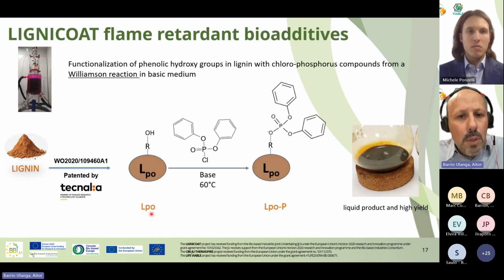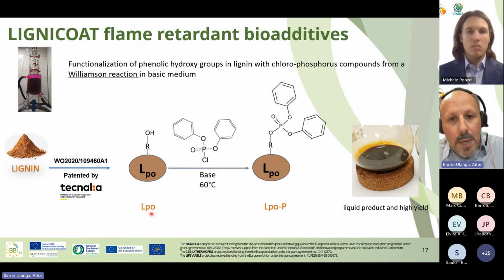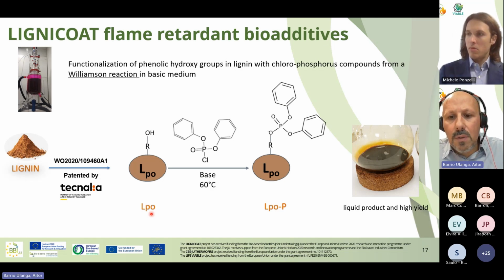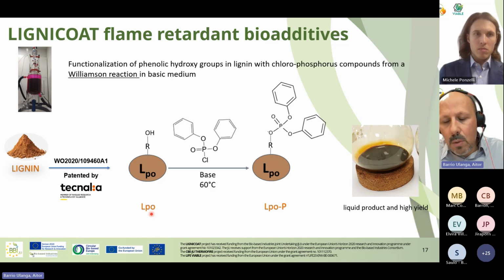So in the case of LIGNICOAT, we decided to produce fire retardants for use in these coatings based on lignin. As the main topic of the project is lignin, we decided to prepare active fire retardants based on lignin. Tecnalia has a patent for the production of polyols from lignin, so we started with these polyols, and we used a Williamson reaction in basic conditions to obtain phosphorylated lignin polyols. It is important that it's a liquid, not a solid, so we can manage it better in coating applications.